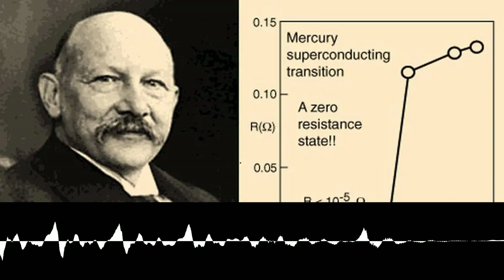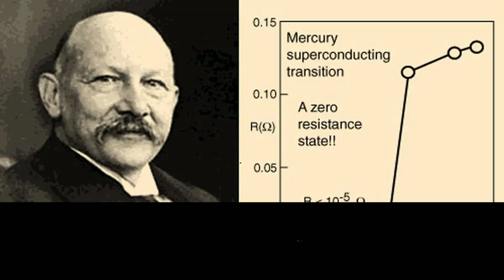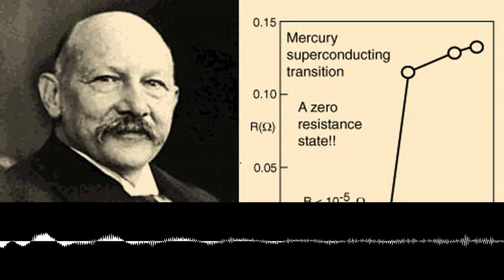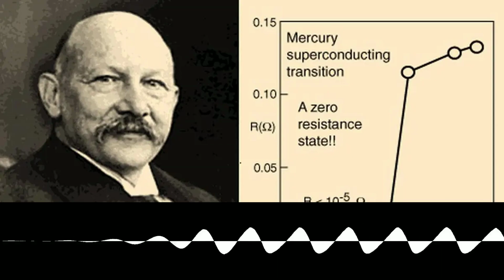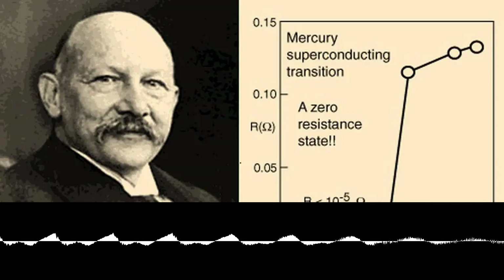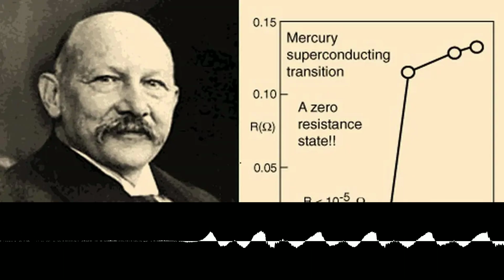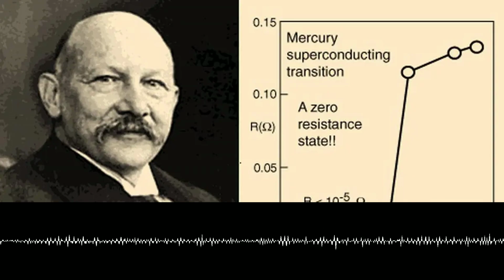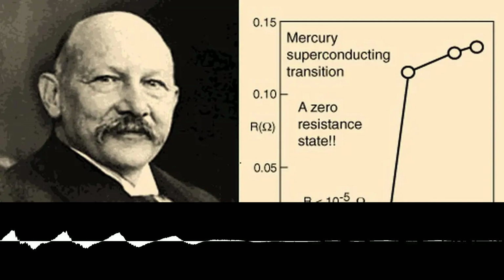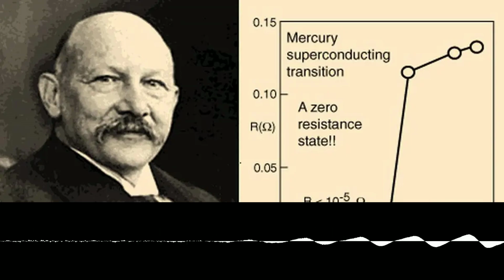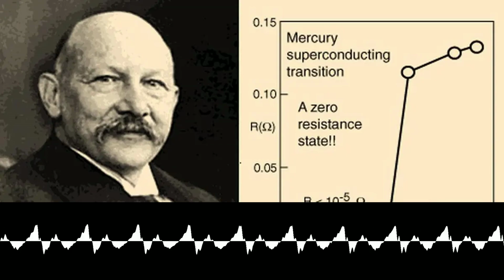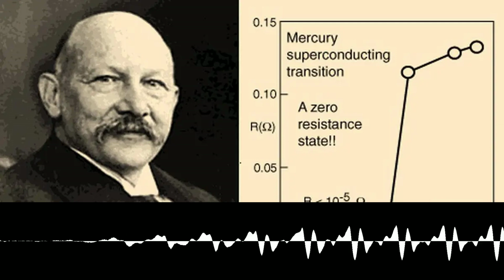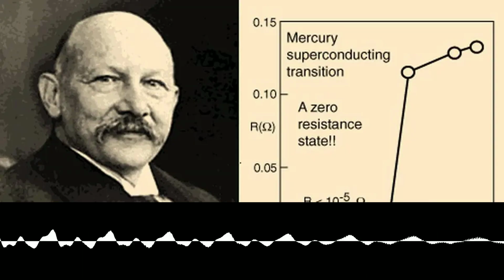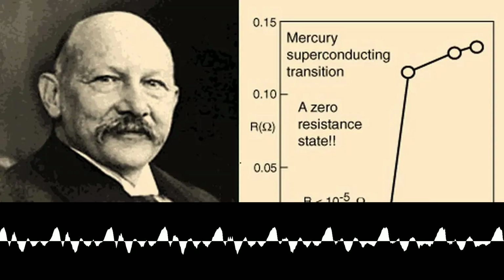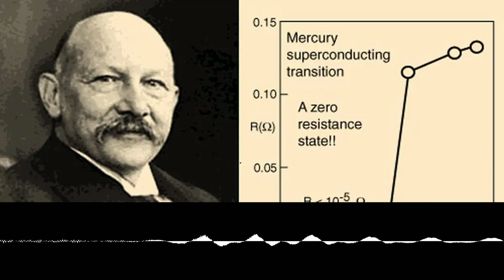Their experimental reports detailed a systematic mapping of this property. They presented data showing that the critical field was a function of temperature. Its value was highest near absolute zero and decreased smoothly as the temperature rose, reaching zero at the critical temperature itself. This established a phase boundary in a temperature-magnetic field diagram, a powerful conceptual tool. An evaluation of their early data suggests the relationship they found was approximately parabolic, a relationship described by the formula H_c(T) equals H_c(0) times the quantity 1 minus the square of the ratio of the temperature to the critical temperature.